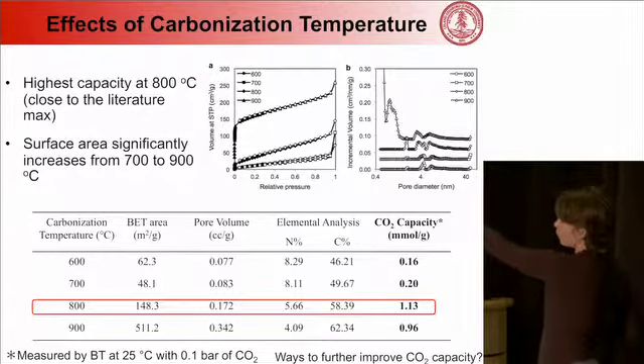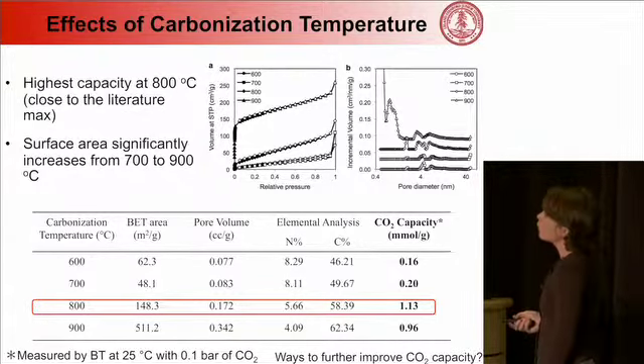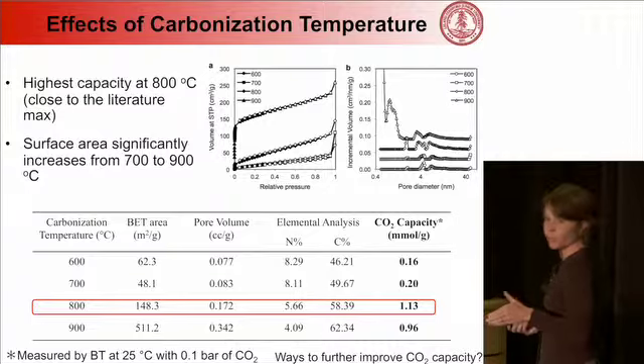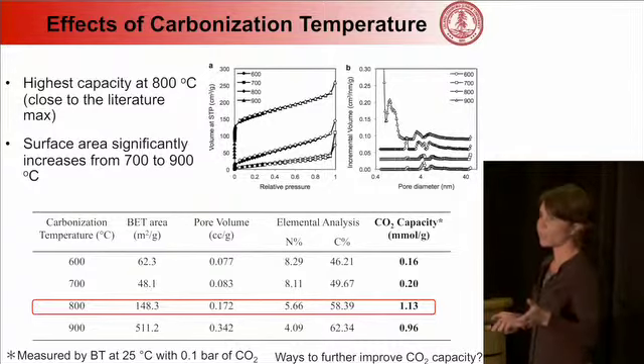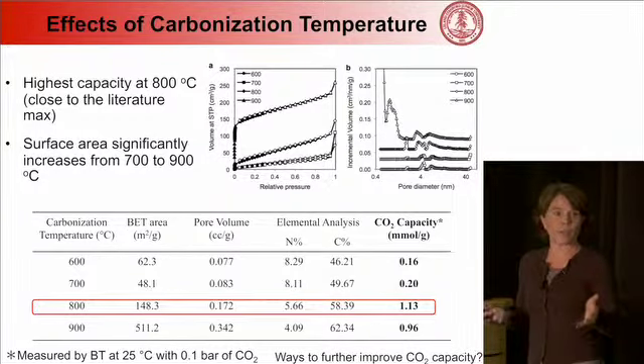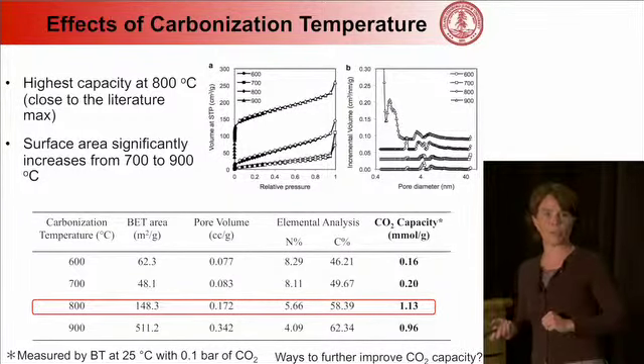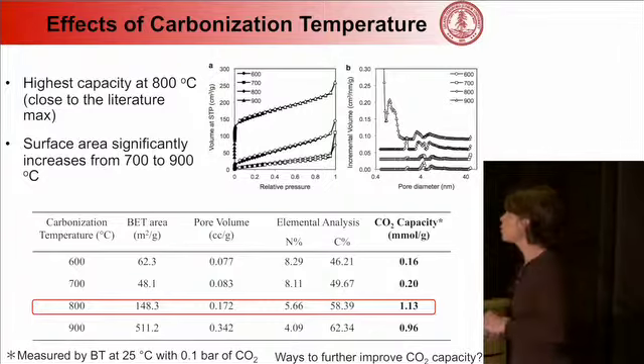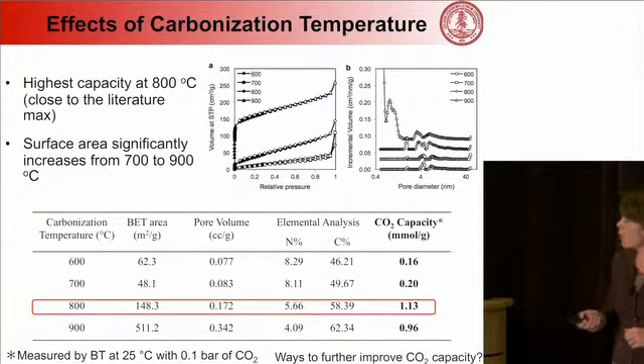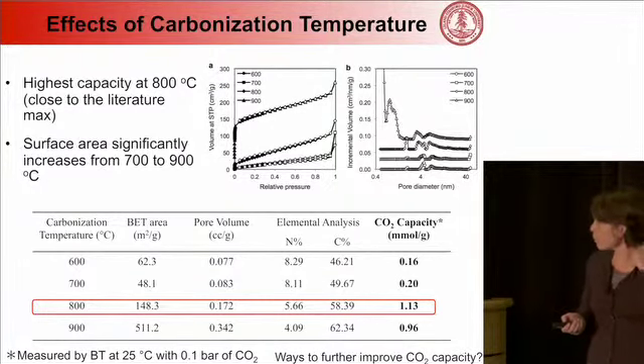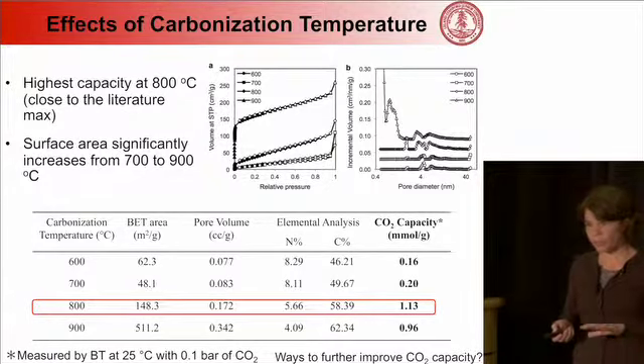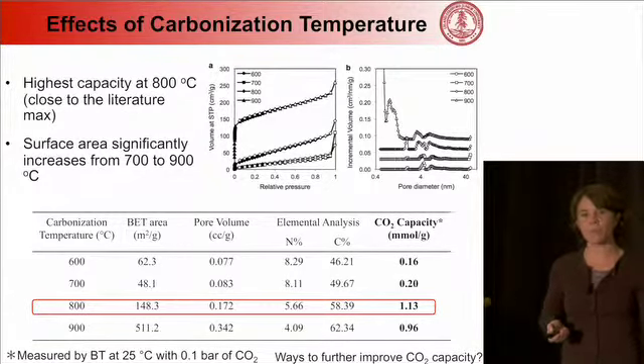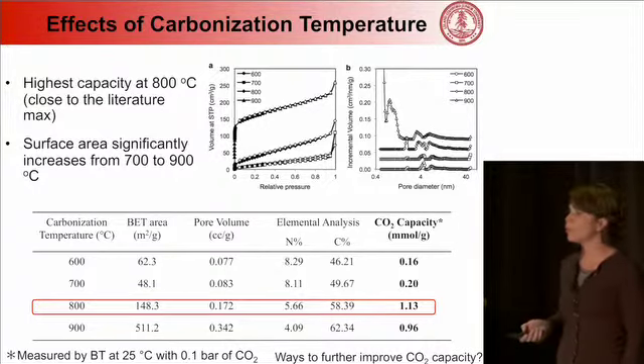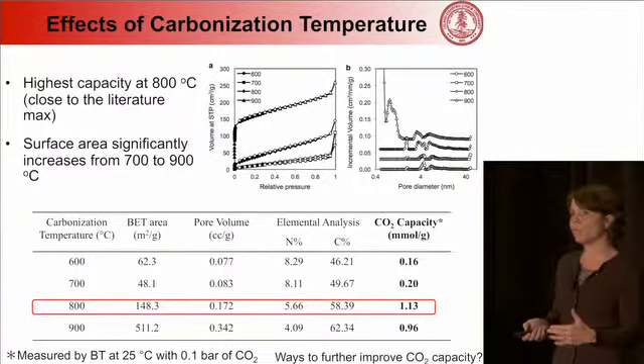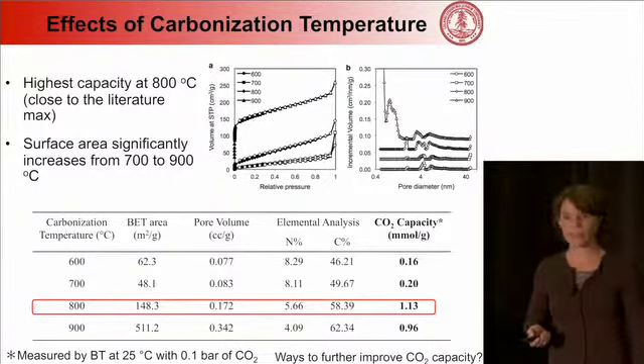So if you look at the top curve, you'll see that the primary pores are associated with very small pores. And in fact, so small that that doesn't actually help us. It may increase the surface area, but it doesn't enhance the uptake of our material. And so pore size distribution is actually quite important. It's one of the aspects that we're focusing on. So the question that we asked with just simply looking at these carbon-based substrates, how can we improve the CO2 capacity of these before we move on and actually functionalize them with zinc?